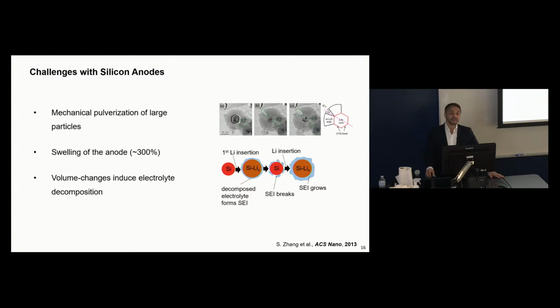So I want to highlight a few challenges. When you insert lithium into an intercalation compound, as I mentioned, there are very little volume changes, so very moderate stresses occur. Silicon takes so much lithium that it changes in volume. And if you have a gradient in lithium concentration across the particles, it may build up internal stresses. If the stresses exceed the value related to the fracture toughness of the material, you may have pulverization. Large particles will pulverize into smaller particles, and the batteries may degrade. Another challenge is that when you lithiate silicon, it expands so much, right?